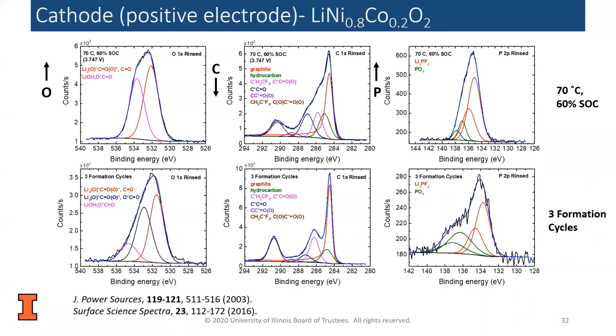Okay, and then here's a comparison of the formation cycle and what's called an accelerated aging test. In this case, the battery is held at an elevated temperature and held at a high state of charge to simulate charging of a battery. You can see now that the oxide signal compared to the carbon is greatly increased. So we're actually covering up much of the electrical network that is the graphite and the carbon black, and covering it with some type of an oxide. It looks like carbonates and hydroxide. And then we can also see that the phosphorus signal has been greatly increased.